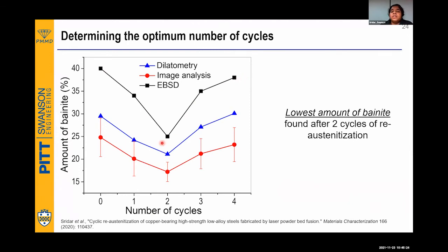Though the numbers are slightly different from each other, one thing we can see is that for the optimum number of cycles, which is 2 cycles of reaustenitization, the bainite content is the lowest, which means the martensite content is the highest. As I mentioned earlier, martensite is the hard phase, bainite is the soft phase. The lesser the soft phase, the harder it is going to be. And hence the optimum number of cycles was chosen to be 2.